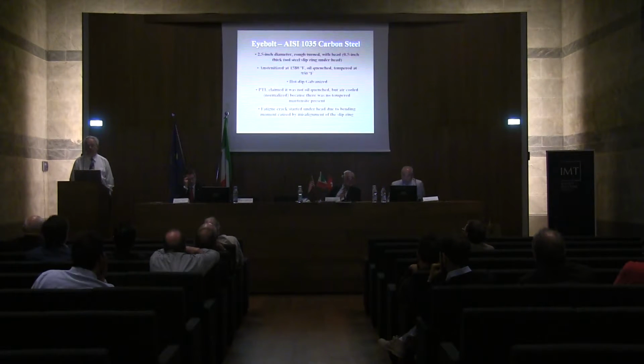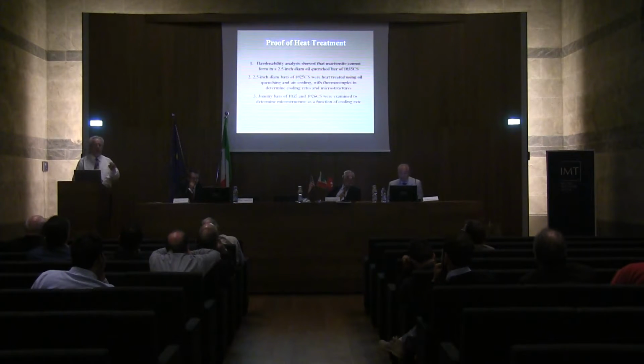Now, as I mentioned, the eye bolt was 1035 carbon steel, 2.5-inch diameter. It was rough turned with the head about 1/2 inch thick. A tool steel slip ring was under the head. The eye bolt was austenitized at 1580 Fahrenheit, oil quenched, tempered at 950 Fahrenheit, then hot dip galvanized. And Pittsburgh Testing Lab claimed it was not oil quenched, but air cooled or normalized because there was no tempered martensite present. Now, a fatigue crack started under the head due to bending moment caused by misalignment of the slip ring. Now, I want to mention one thing.